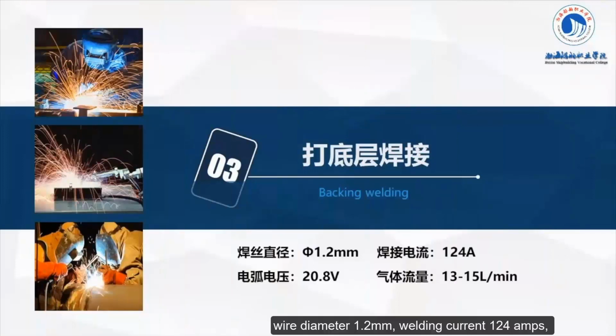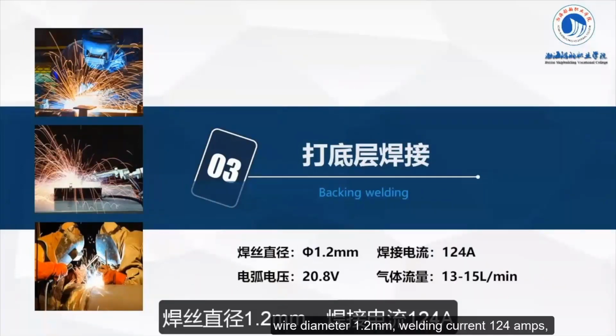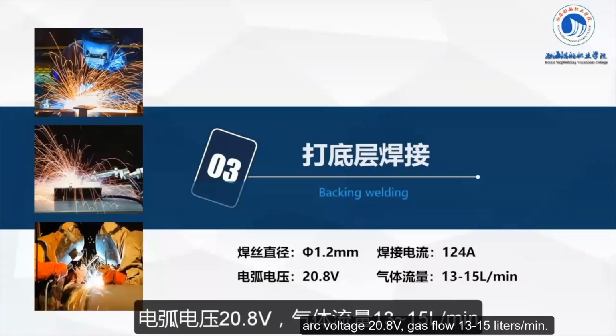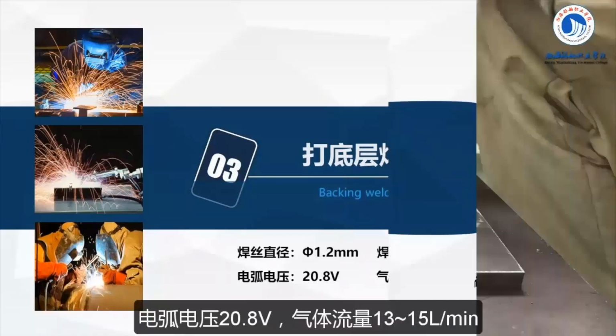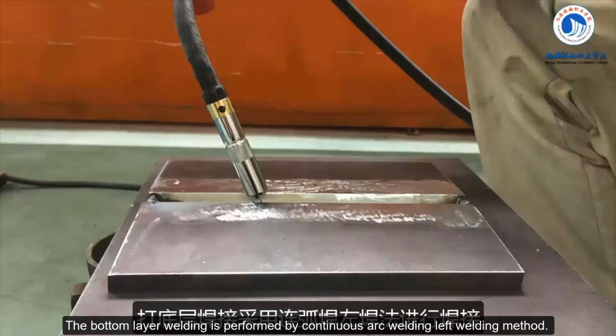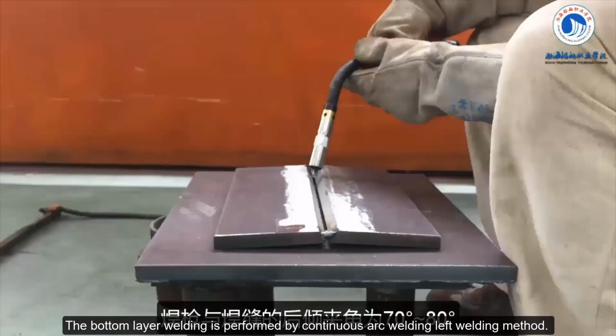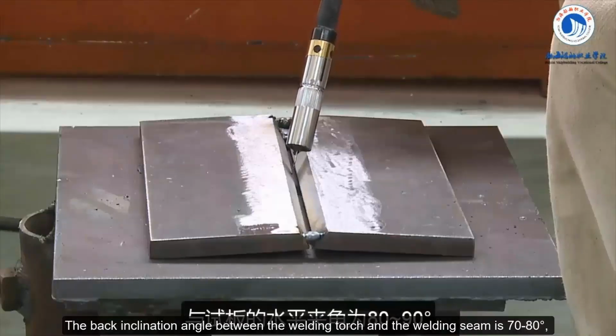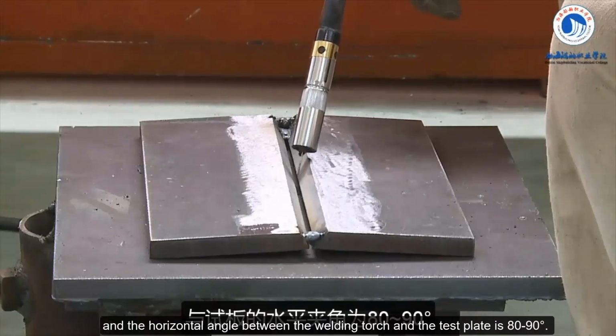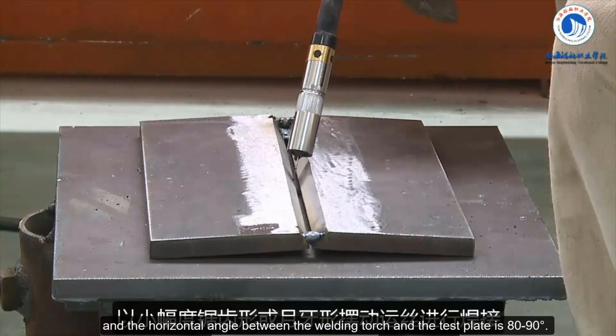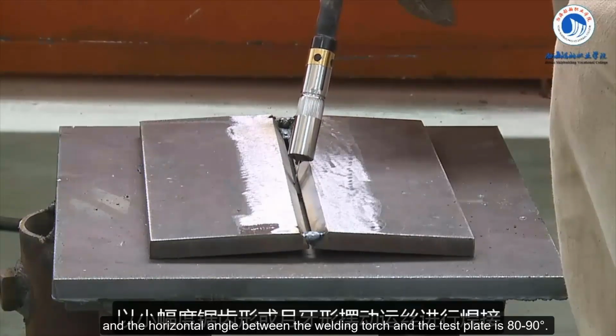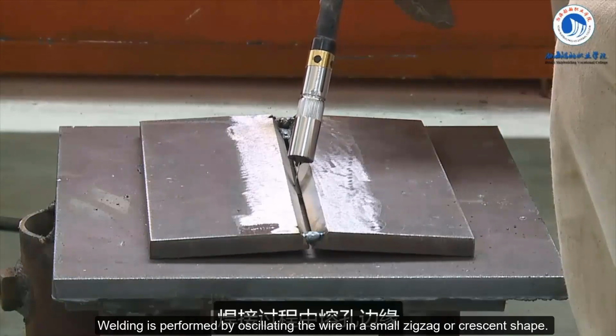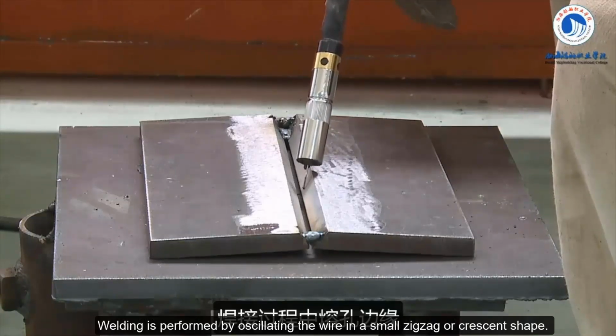Bottom layer welding. Wire diameter 1.2 mm, welding current 124 amps. Arc voltage 20.8 volts, gas flow 13 to 15 liters per minute. The bottom layer welding is performed by continuous arc welding left welding method. The back inclination angle between the welding torch and the welding seam is 70 to 80 degrees, and the horizontal angle between the welding torch and the test plate is 80 to 90 degrees. Welding is performed by oscillating the wire in a small zigzag or crescent shape.